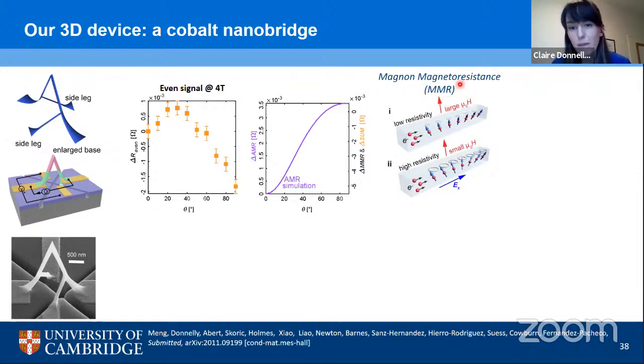So a quick reminder of what the magnon magnetoresistance is. The idea is that we have magnons in our magnetic material that result in scattering from the electrons. Now, when we apply a large magnetic field, we can suppress the magnons, we can suppress the precession of the spin, and lower the resistivity of our material.